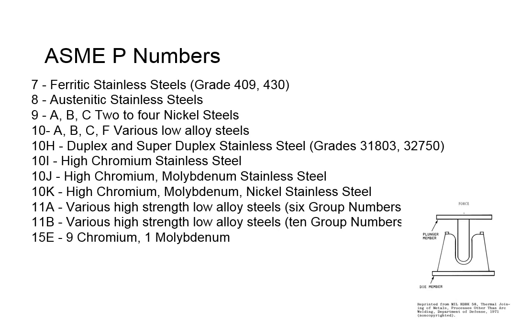Here we've got ferritic stainless steels, austenitic stainless steels. Group P10H, I've dealt with duplex stainless steels. Generally there you're trying not to put too much heat into the material because that'll just mess it up. So you want to keep your heat inputs on that material generally pretty low. Any weld procedure you qualify with that, you've got to keep your interpass temperatures low.